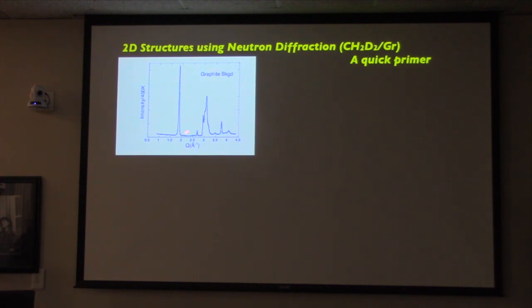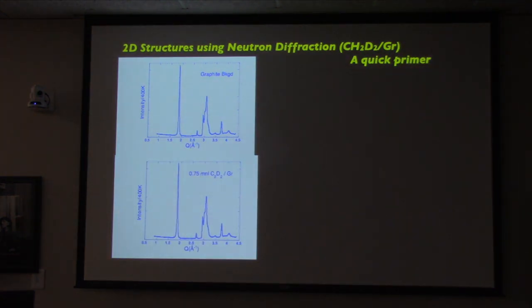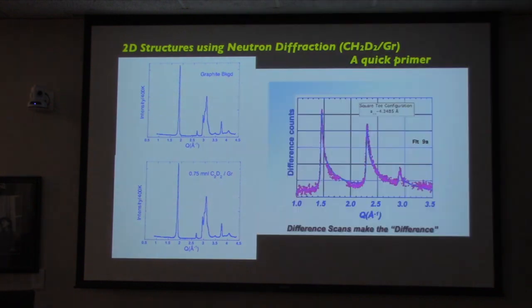So this is the diffraction experiment with neutrons from a graphite sample. It's vermicular graphite. It's crystalline. And you'll notice that why it is that I do what I do is because if you adsorb something like a single layer of acetylene on the surface, then you can see the big difference between the two. And that's shown here. So now you know why it was that tenure happened at Brookhaven, et cetera, right? Oh, wait a minute, maybe I should take the difference between the two of those.